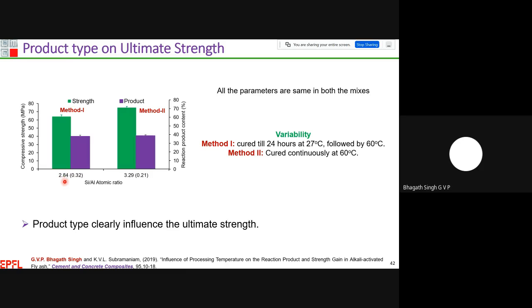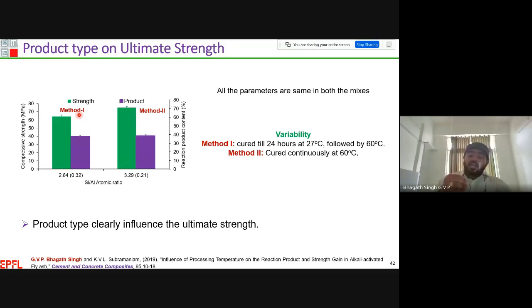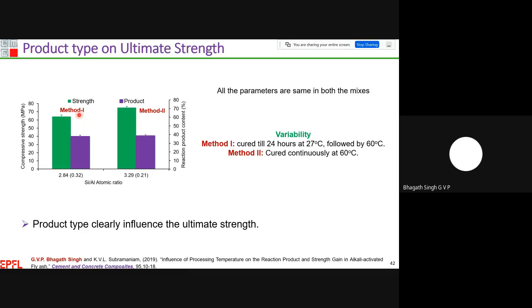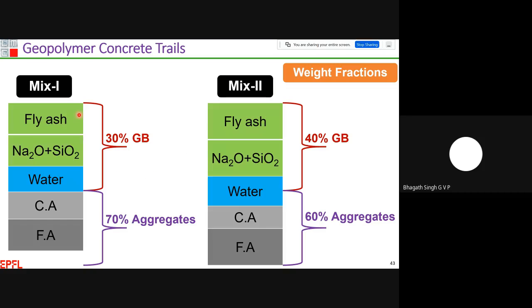which means by increasing the silica to alumina atomic ratio from 2.84 to 3.29, there is an increase in the compressive strength of about 10 megapascals. So the silica to alumina atomic ratio in the microstructure clearly influences the ultimate compressive strength of our fly ash based geopolymer. And if time permits, maybe I would like to show some of our trials.